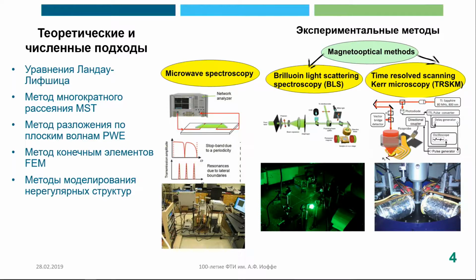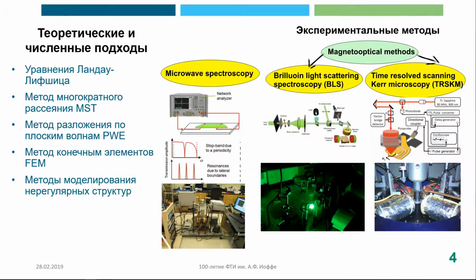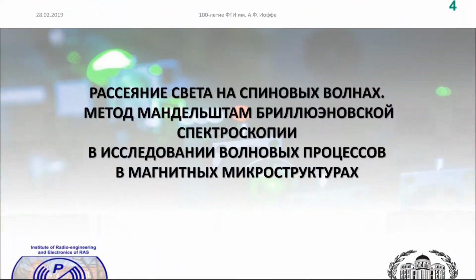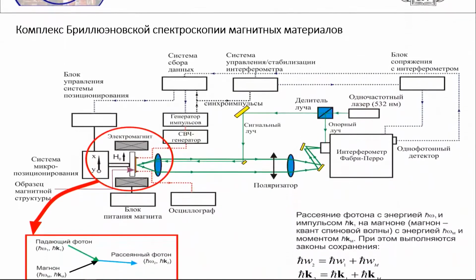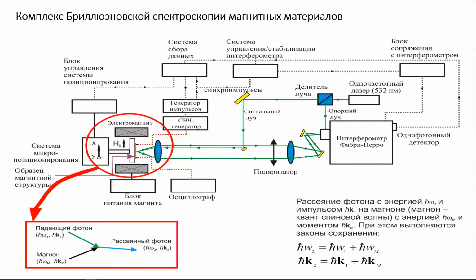Therefore, you can go with scanning. You will see some result of this scanning of structures or surfaces of the structure with a diameter of the spot of less than 1 micron, so it's over the optical limit of possibility of this description of these materials. Therefore, this complex of Brillouin light scattering spectroscopy of magnetic materials includes a Fabry-Perot interferometer. They then include some microwave system for excitation of propagating spin waves and some quite complicated system of developing of the signals. So what kind of signal can we see?